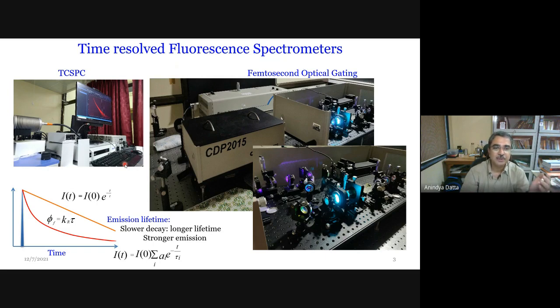And in the simplest case scenario, the decay is of first order. This is the same integrated rate law for first order reactions that we have studied. It's just that instead of population, we have written fluorescence intensity I at time t and I at time 0. Time 0 is the time at which the laser pulse hits the system. And the other difference is that conventionally, we don't write the rate constant k, rather we write the time constant tau. And in case the decay is single exponential, this time constant tau is the average life spent by the system in the excited state. So it is called the lifetime.